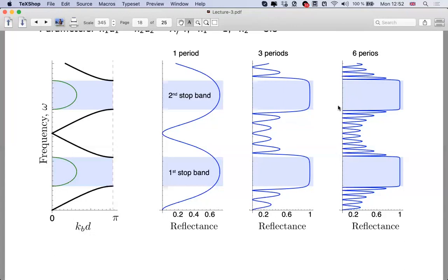And actually, there is an interesting paper by Mikhail Rybin and Mikhail Limonov. After the fabrication of this photonic crystal using a nano 3D printer, they measured the diffraction patterns, calculated the number of these intermediate maxima, and then calculated the number of periods in the photonic crystal. Then they compared this number with a real image from a scanning electron microscope. And of course, it was the same.